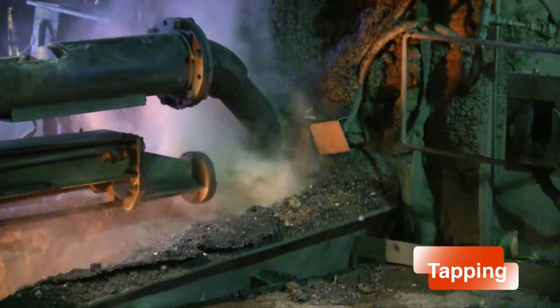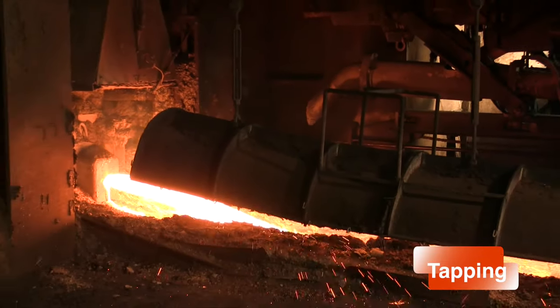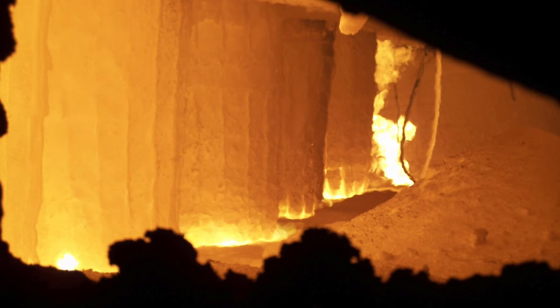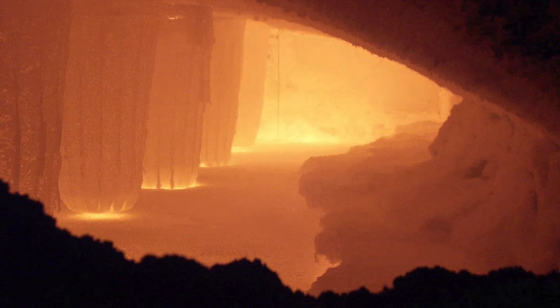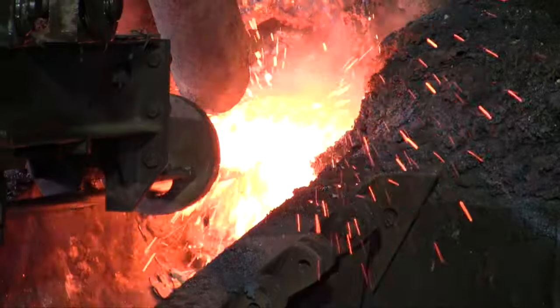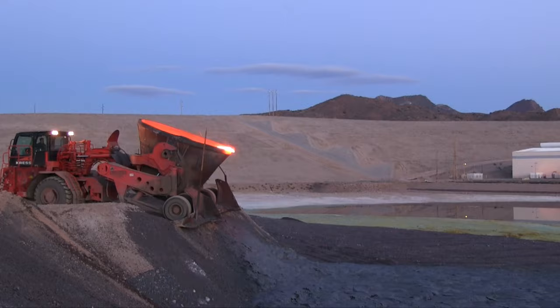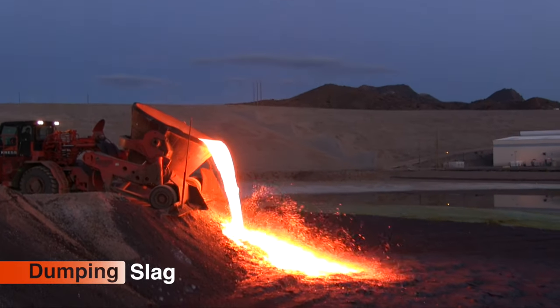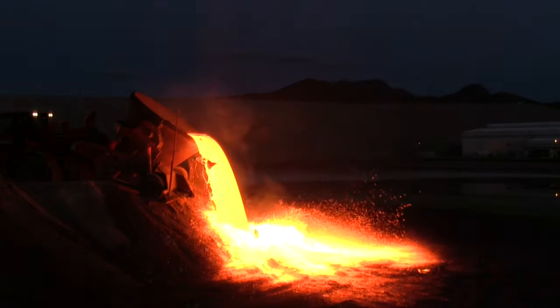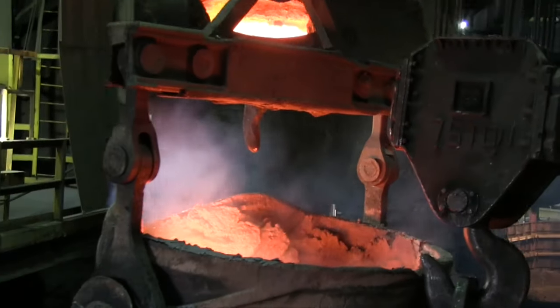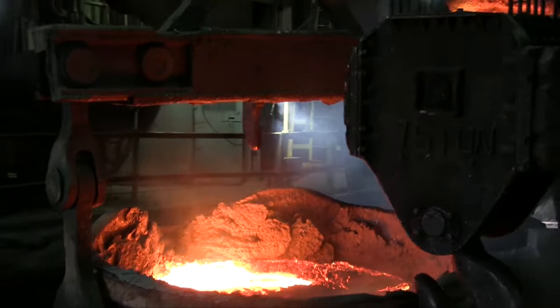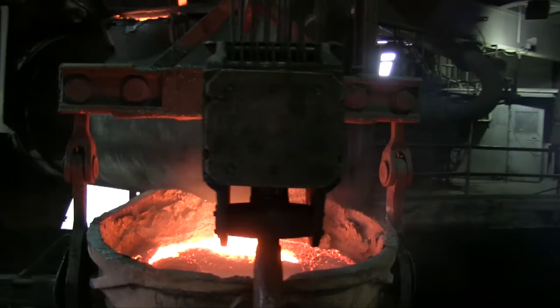We tap the molten material from the Isasmelt furnace into an electric furnace to separate copper-bearing matte, which settles under the lighter waste called slag. We skim off the slag by tapping it through a hole at its level of the furnace, and we haul the slag to a dump where it remains inert. Using massive ladles moved by overhead cranes, we send the matte copper to converters for further processing.